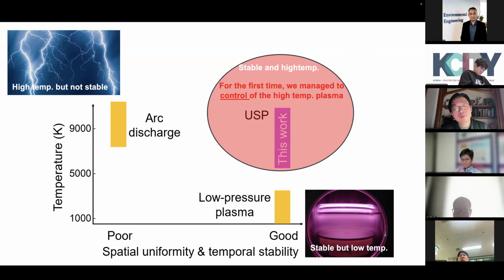Lightning is not a constant, stable behavior. It comes, it goes, right? It's a linear behavior, and it's very high temperature, but it's not stable, right? So if you're using almost like arc discharge, you can use that to make materials, but it's not stable. That means it's really hard to get a stable yield. Very often you have to cook it again if you're trying to make the material. So as a result, you're wasting energy.